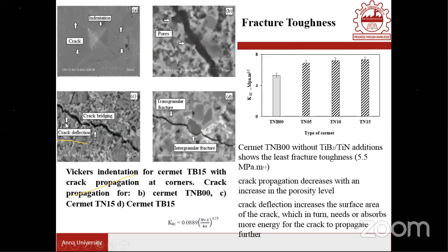One can witness several mechanisms in the microstructure. That is, crack bridging is also there. Crack deflection is also there. You can see the crack deflection as well as crack bridging in image C, as well as transgranular fracture and intergranular fracture. If you want to split the particle, you need more energy. That means the crack will be propagating across the particle. And if the boundaries are strongly bonded, then to separate the boundary, you need more energy. That means these are the extrinsic mechanisms by which you can improve the fracture toughness value.